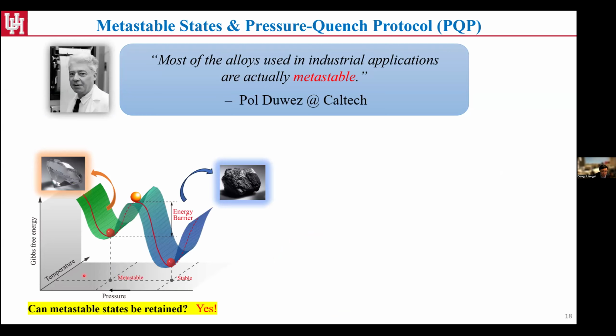While here the phase diagram may not be, as one colleague pointed out earlier, really scientifically correct, the real 3D or 4D phase diagram will be way more complicated. But here we're just trying to show you a concept: by adding pressure, we are tuning the material state from stable to metastable. And in this dynamics, we create an energy barrier. One mechanism we're thinking of is that if this energy barrier is high enough, and if we find the correct path or a sweet spot to release the pressure, this barrier could help us keep this metastable state, preventing it from coming back to its ground state or relatively stable state.